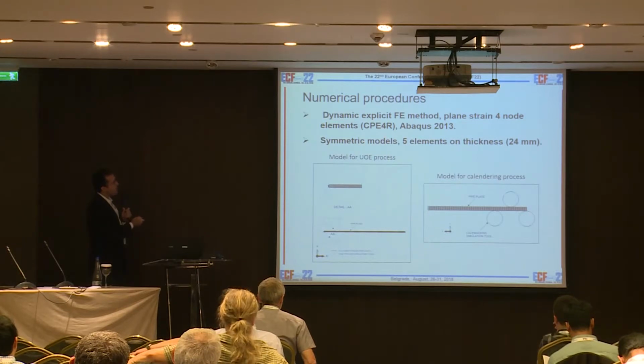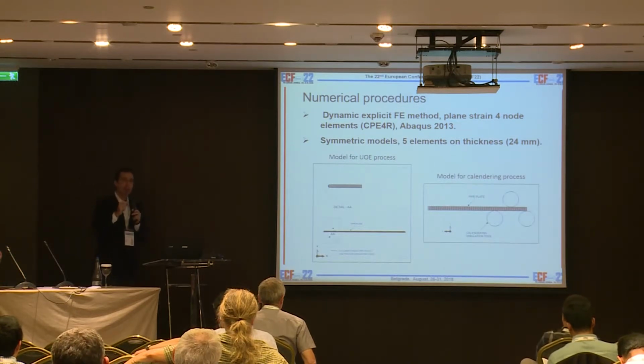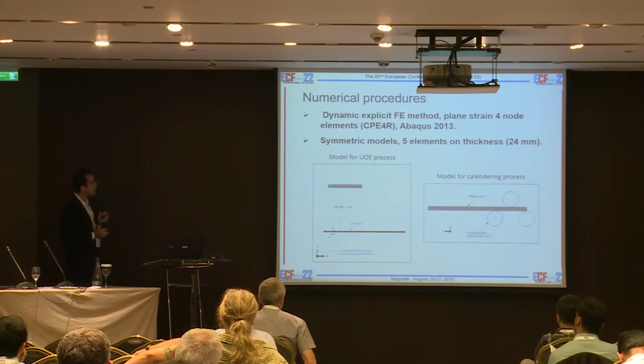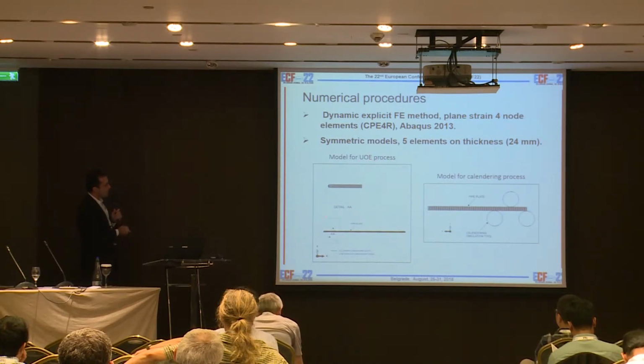The models are symmetric. We employed 5 elements on thickness because we detected that with more elements, the strain field did not change anymore. So to save some computational resources, we did it. And the thickness in this case was 24 millimeters. Here is an example of the UOE process. The tools are considered rigid.